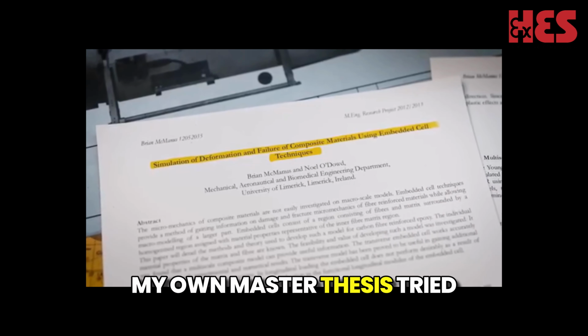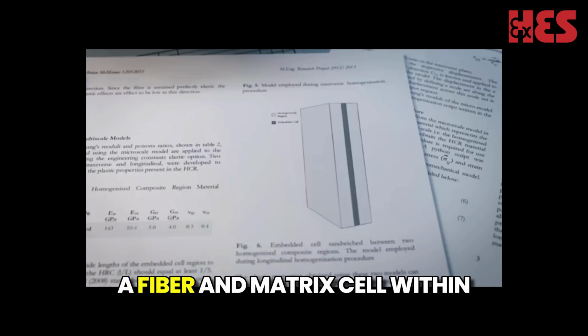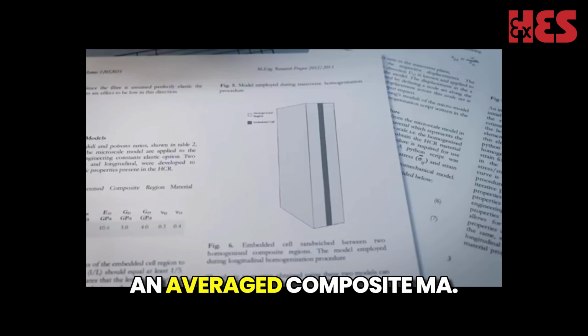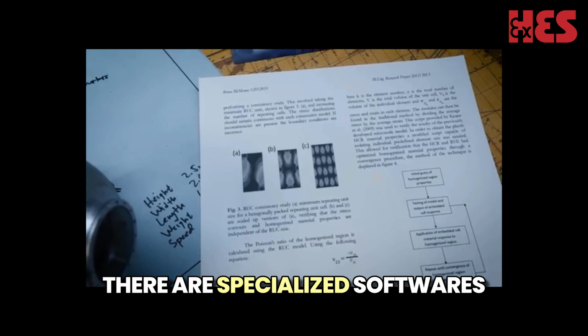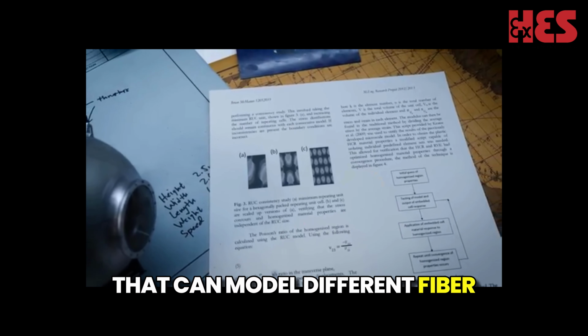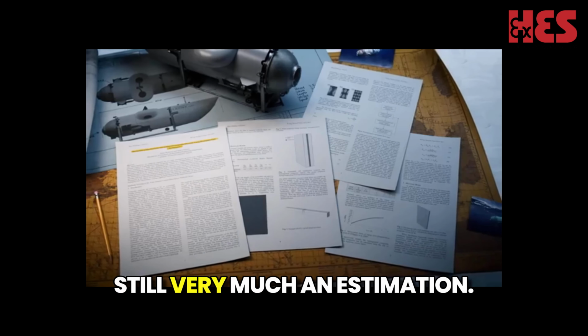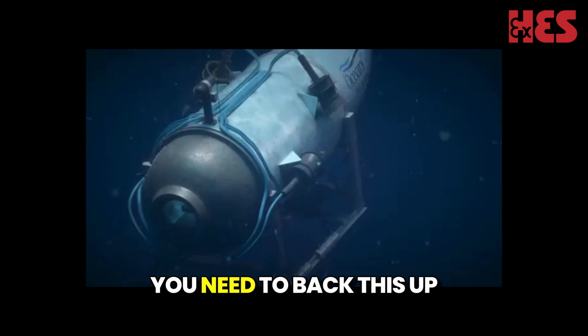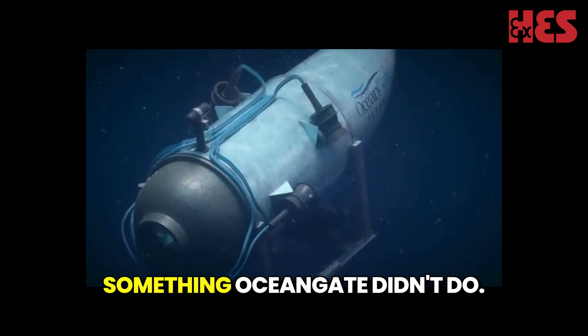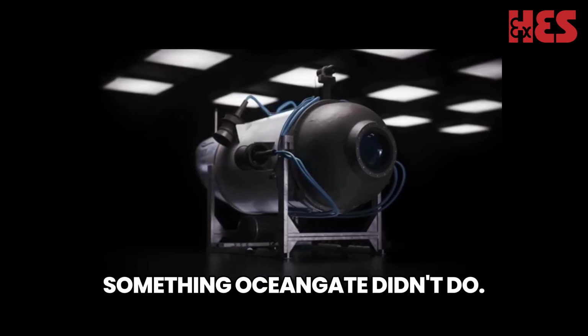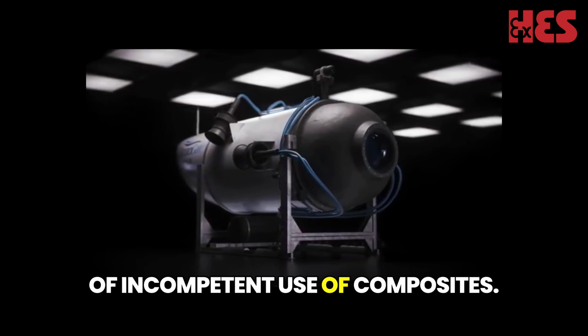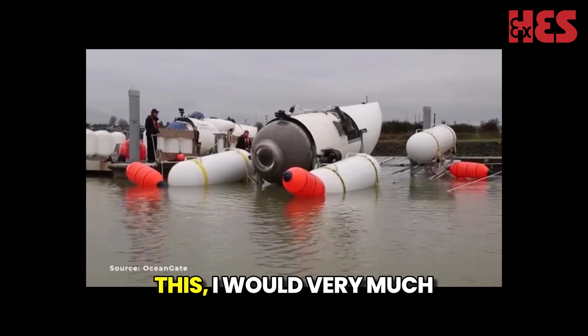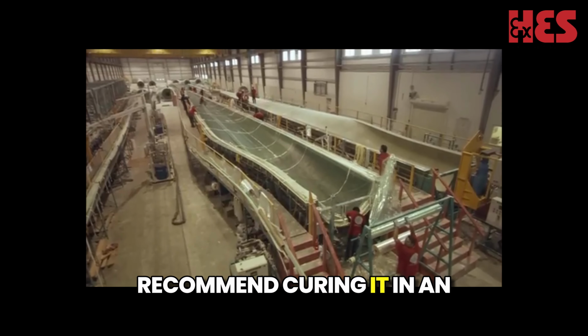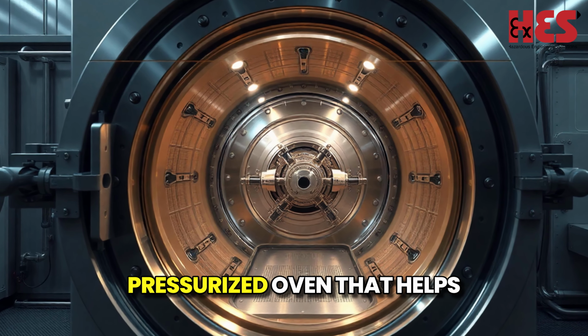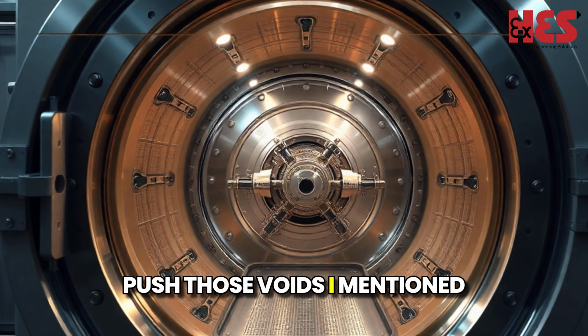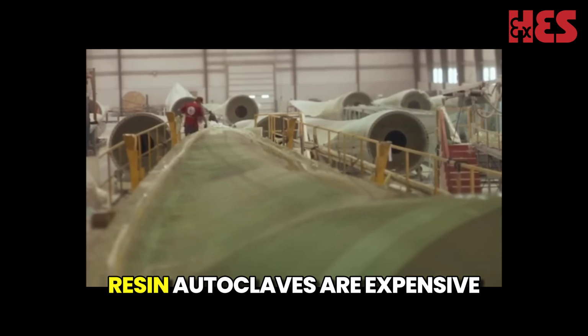My own master thesis tried to combine the two by embedding a fiber and matrix cell within an averaged composite material. There are specialized softwares that can model different fiber orientations, but they are still very much an estimation. You need to back this up with physical testing, something OceanGate didn't do. There are more signs of incompetent use of composites. For a critical structure like this, I would very much recommend curing it in an autoclave. That's basically a pressurized oven that helps push those voids I mentioned earlier out of the epoxy resin.